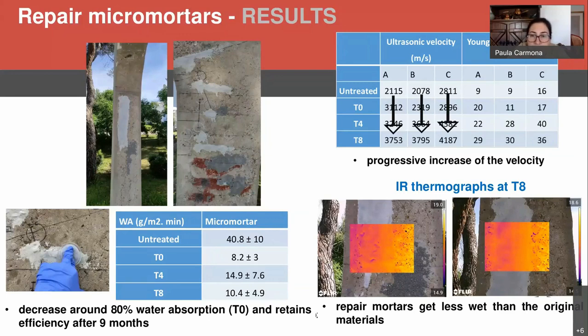And also we can see in the infrared images how the chemical admixtures that were introduced in the matrix induce the hydrophobic properties of the mortar. You can see here that the material, the micromortar, gets less wet than the original concrete, as you can see here in the infrared images. Next, please.